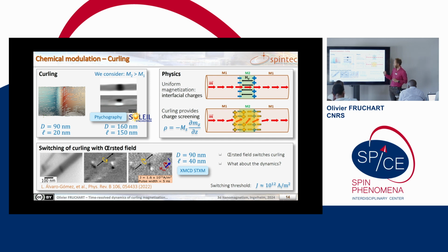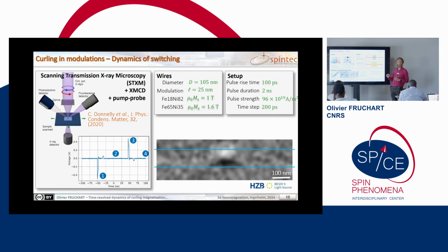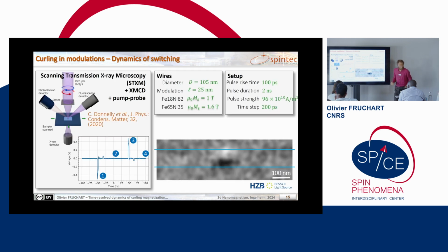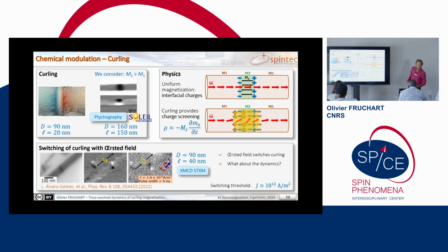What happens if you make some curling is that you create some volume charges which tend to screen the 2 planes of charges. So instead of having a dipole, you have a quadrupole, and you decrease the magnetostatic energy, of course, at the expense of exchange, because you have to rotate magnetization along the length.